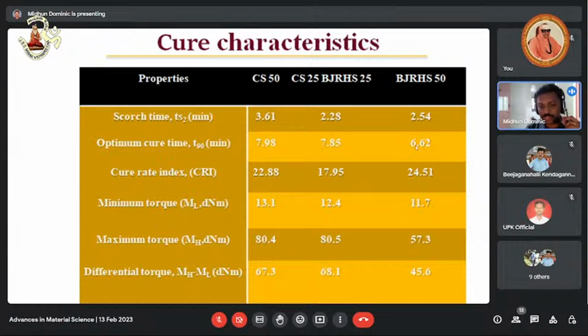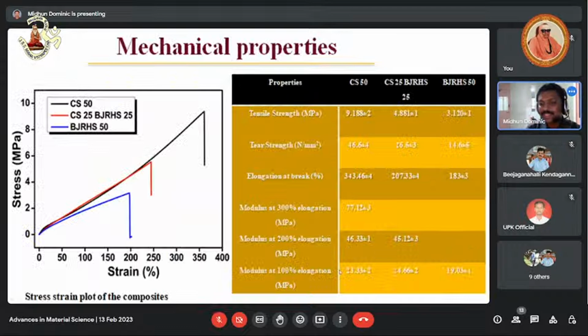We can save energy. But what about the differential torque? Differential torque determines the number of cross links formed during the vulcanization. But the cross links were significantly fewer. It is only 45, and here it is around 68. And look at the tensile strength and tear strength measurement. First, we thought we had prepared a nice material with excellent surface area, extreme purity and low particle size. But we are disappointed with the results, because look at the tensile strength results.